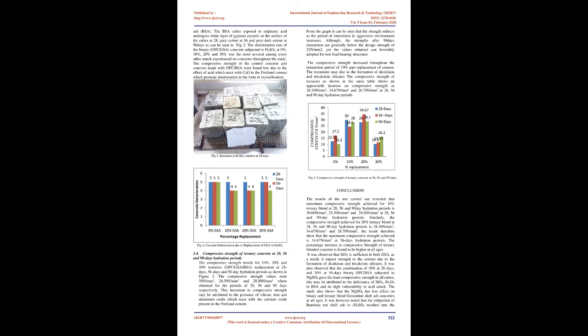The concrete deterioration observed was connected to deficiency of calcium oxide, CaO, in groundnut shell ash, BSA. The BSA cubes exposed to sulfuric acid undergo a white layer of gypsum crystals on the surface of the cubes at 28 days, gray color at 56 days, and gray dark color at 90 days, as can be seen in Fig 2.